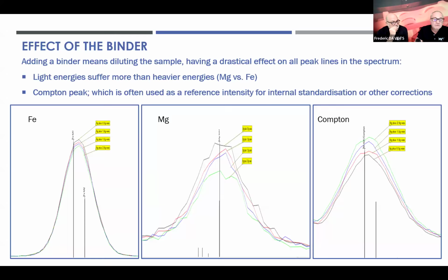And for the lower one, so the green peak, we had a dilution of 9 grams of sample to 2 grams of wax. So we can see a very clear difference in intensity here. And this is even more obvious for magnesium, so for a light element. And here we can really see huge differences in intensity. So we understand that it is important to have very strict conditions and always use the same amount of binder for similar types of samples.